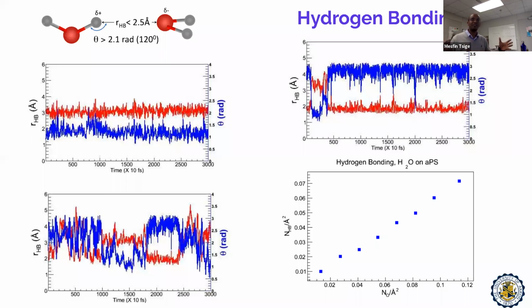But interestingly, once it reaches equilibrium, the number of hydrogen bonding stays constant, stays fluctuating about a certain value. And when we look at that number of hydrogen bonding as a function of degree of oxidation, the degree of oxidation we talked about, we see this linear dependence. And that linear dependence, we believe, is the reason for the linear decrease we saw in the contact angle as we measure, as we change the degree of oxidation.